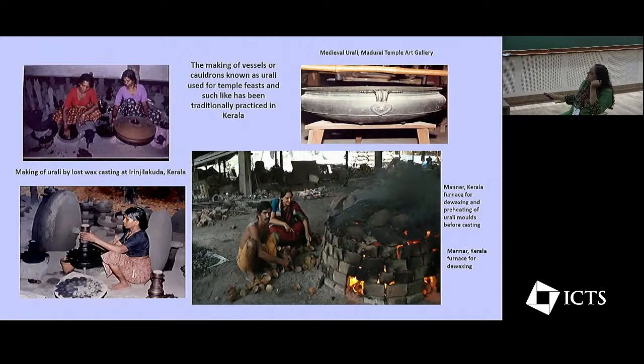And this addition of lamp black on the surface of the wax, the last layer, is very important, because when the mold is heated, this becomes a very adsorbent, carbon-rich layer, so it can absorb all the gases right out of the mold. Because if you don't absorb the gases out of the mold, it will actually give a very bad surface, and so you have to do much more finishing. So there are a lot of little nuances where even using just organic materials, you're getting a very good casting.